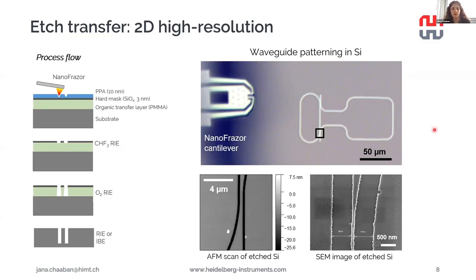In this first image, you see how the design is patterned onto the thermally resistive PPA layer. This is actually an image taken from the NanoFrazor software tool itself. And below you see how it nicely transferred onto the silicon after etching. You can see an AFM image of it and also an SEM. And this shows that our initial feature sizes are nicely reproduced in silicon. And of course here the edge roughness can be smoothened out if we use smaller pixel sizes in our initial design. So all of this can be tuned.